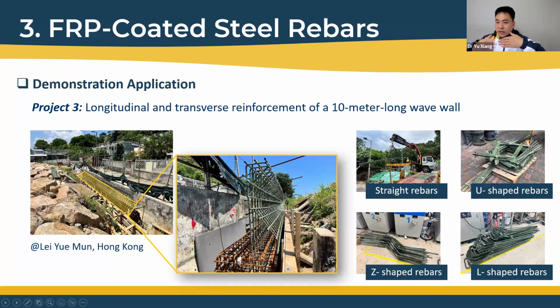Because for this project we call this wet bending. What does that mean? We apply the coating layer, and before hardening, we do the bending. Then we put these specimens or rebars into an environmental chamber to make it harden. So for this coating angle, we think there's no problem.